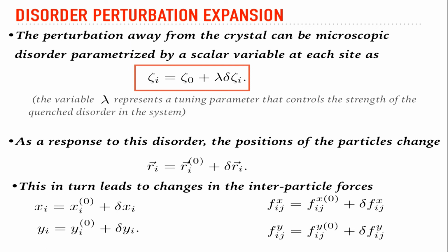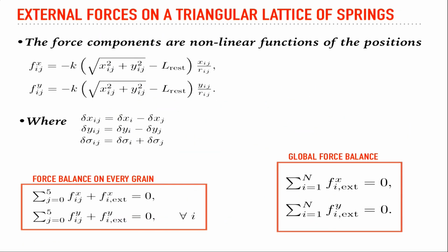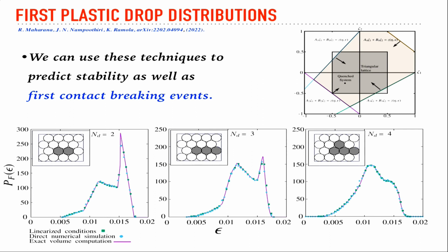How would introducing disorder, let us say polydispersity, affect the fracture properties, for example? That's a very, very interesting question. This is actually related to what we're studying here in the stability criterion. I have not plotted it here, but this is introducing polydispersity. This is like a fracture property, the breaking of a contact. This is a global property of the system. It's like a fracture, but not a crack propagation. It's just one contact breaking. But once one contact breaks, the system is more amenable to other contact breaking events, so this is indicative of when a fracture would occur.